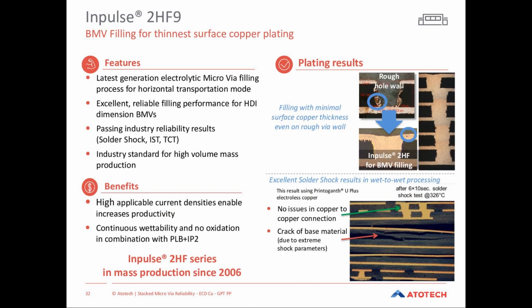After flash plating, you need the copper filling, and also here we have for horizontal a very well established, but meanwhile improved process called Inpulse 2HF9. And this process gives you an unmatched copper filling, which means you can fill really large and deep microvias with a very, very low plating thickness on the panel surface. So this process is one of the standards for any layer and HDI application in the industry.